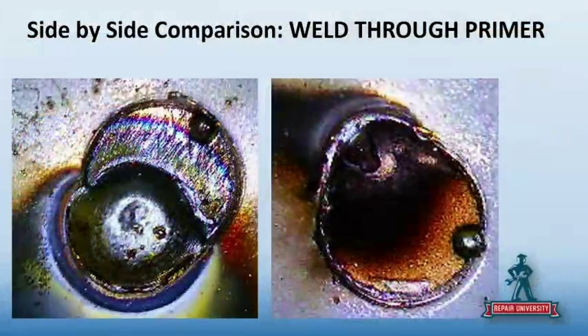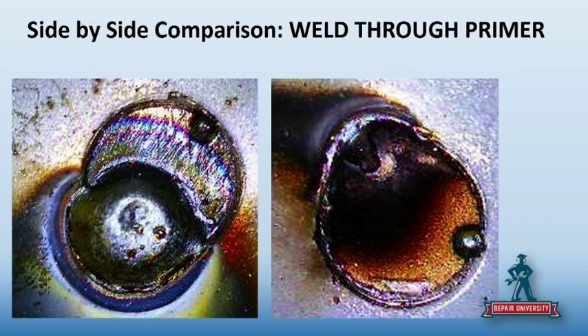So now what happens is you spend so much more time trying to recover and make a good weld that you spend much more time in the weld zone. So you're going to get a hotter weld. So you get a poor quality weld, you get a hotter weld that destroys the metal, and you burn away all the coatings. But I've been doing this 30 years. I've been poorly welding for 30 years. And it just burns out, doesn't it?